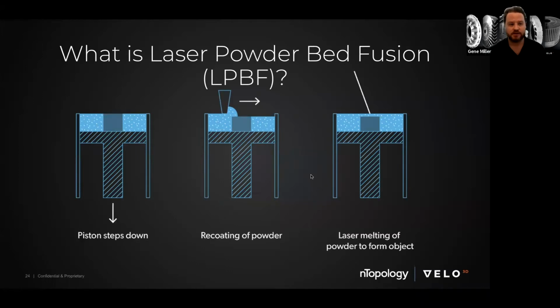what a laser powder bed fusion system does. In a conventional sense, you'll have a piston inside a cylinder that moves down a designated length of distance, and that's your layer thickness. In our case, it is 50 microns. And then in the middle here, you see what we call the recoater. On a conventional metal AM system, I like to call it a dump and smear method. It kind of just plows a bit of powder over the top of the part and leaves a thin thickness of powder to be melted selectively by the laser. Every layer happens iteratively, and eventually it builds up to complete your printed part at the end of the day, and then all the unfused powder is removed and recycled. But that is essentially on a high level how a typical laser powder bed fusion system works.